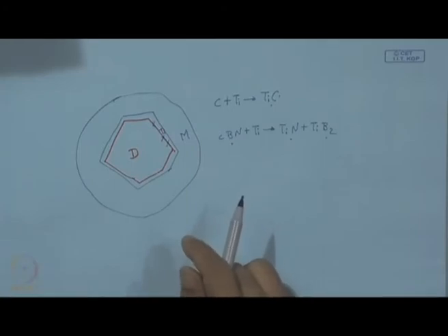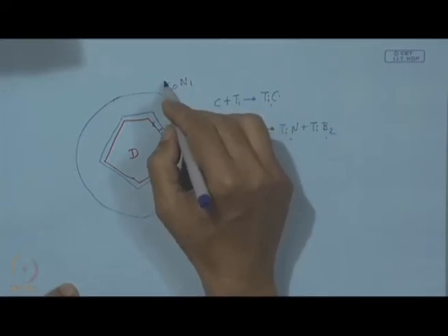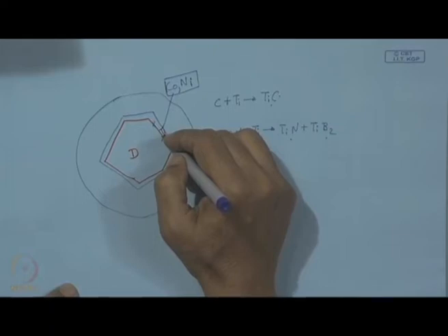However, it is also observed that in certain cases this metal matrix, which may contain cobalt, nickel, particularly this material, during this high temperature processing can also attack diamond. So, in that case, if we have a coating of titanium, that attack chances are remote and that titanium coating actually is protecting diamond.